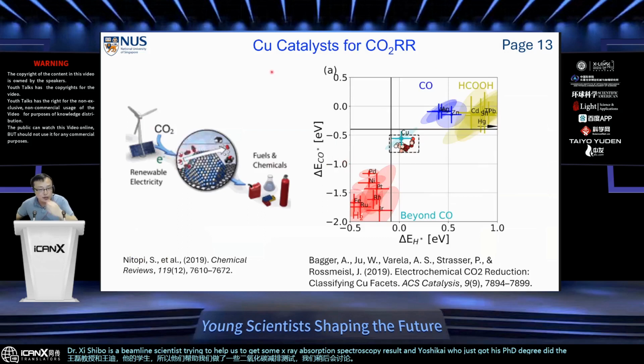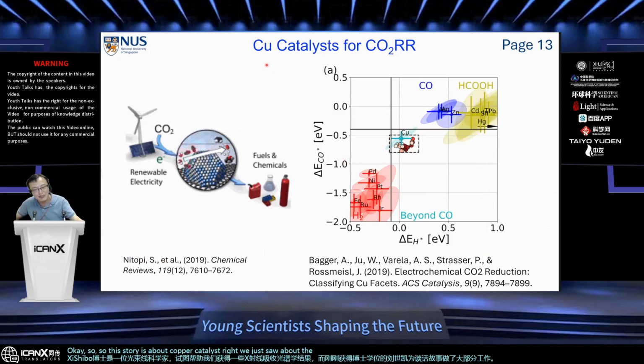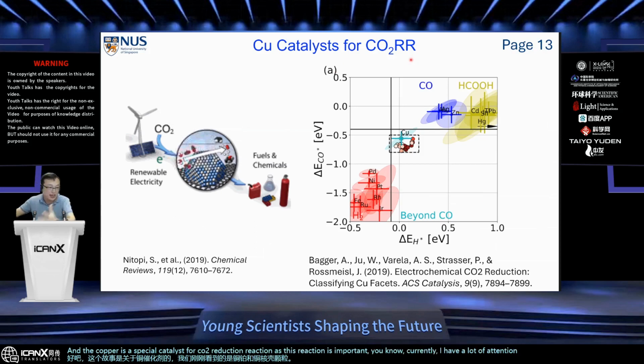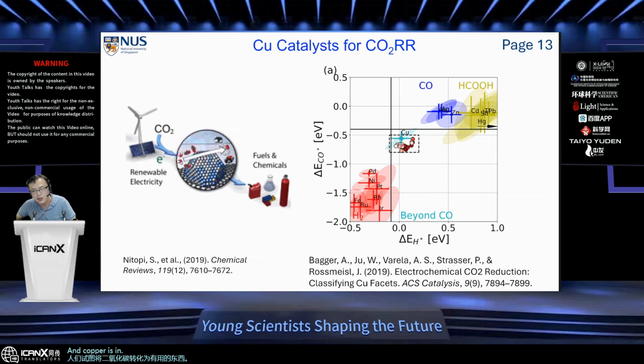Okay, so this story is about copper catalyst, right? We just saw copper, palladium, and the copper core shell particles, and this is just the copper. And the copper is a special catalyst for CO2 reduction reaction. And this reaction is important. Currently it has a lot of attention because of the sustainability challenge, right? People try to take the CO2 and convert it into something useful. And copper is in a very unique position.